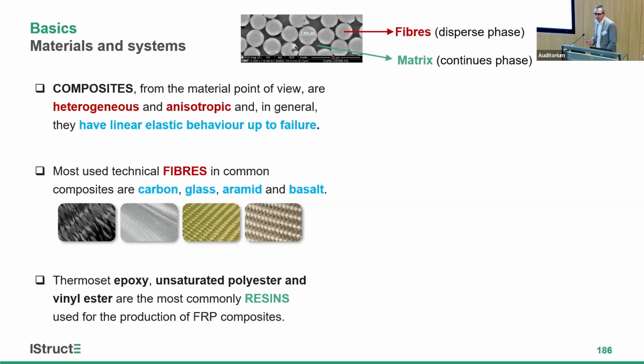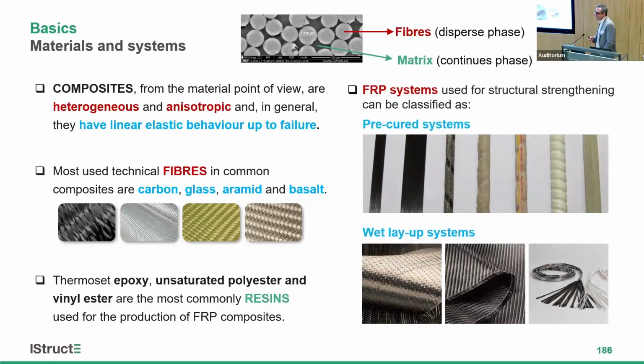The typical fibers that you use in structural engineering are carbon, glass, aramid, and basalt, while in the case of the matrices, normally you use epoxy, unsaturated polyesters, or vinyl esters. The typical FRP systems that we use for structural strengthening of concrete structures are the ones that you can see here, precured systems that already include the matrix and the fibers, while in some cases you use these wet layup systems that we have seen, for instance, this morning for shear strengthening, where we apply these FRP sheets with an adhesive that at the end creates the composite.